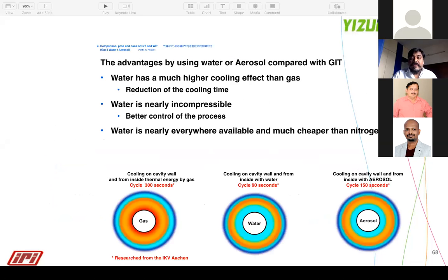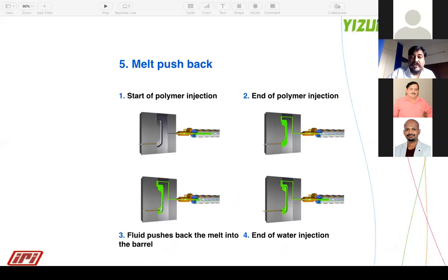You can see here the comparison. The first slide shows the gas injection system, where the cycle time is approximately 300 seconds, but if you use the water injection system, cycle time comes down to 90 seconds because we use cold water. We use hot water to purge out the material and cold water for the cooling. So you can use both the purging out as well as cooling inside the part, so the cycle time can be significantly reduced.